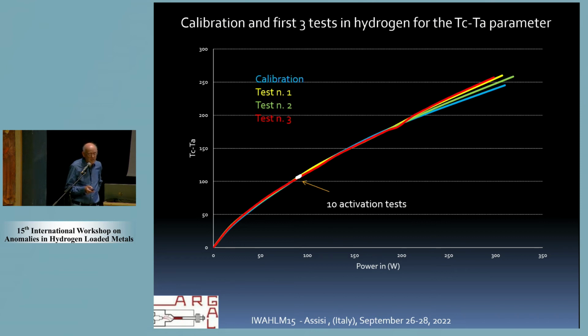This is the same experiments considering the temperature of the reactor respect to environment temperature. You can see that the effect of extra heat for the temperature of the reactor begins a little bit later respect to the internal temperature. This is due to the fact that the reactor is quite big and we have dispersion of the heat produced by the material in the center of the reactor, and dispersion of energy to the edge of the reactor.